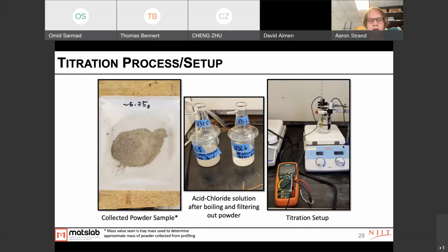So for the titration process and setup, we collected the powder sample for each of the layers, and then we used a nitric acid solution and boiled the powder inside the solution in order to extract the chloride from it. And then the solution was filtered, and we used a titration setup in order to determine the equivalence point of it, and that allowed us to figure out the chloride content as a percent of the amount of concrete.